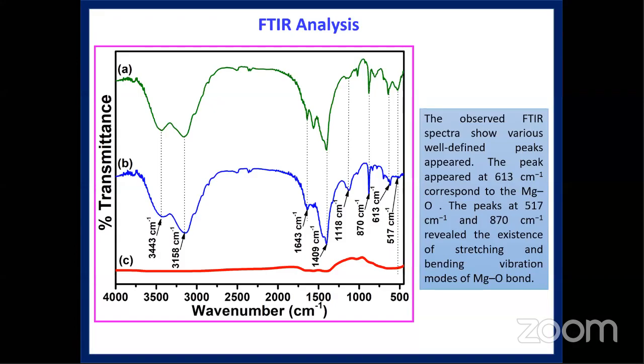And FTIR, what are the functional groups? What are the metal functional groups present in that compound? We can observe from that FTIR analysis that the stretching and bending vibration modes of magnesium to oxygen occur in the range of 870 cm⁻¹ as well as 517 cm⁻¹. The peak appeared at 613 is also a corresponding peak of this MgO.